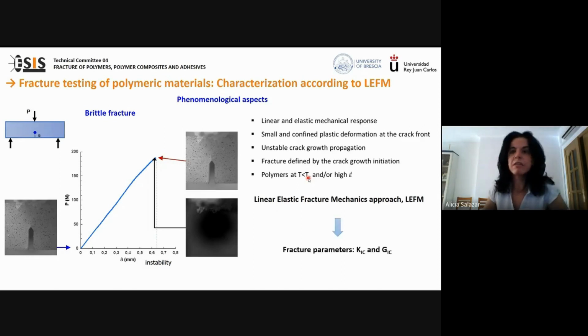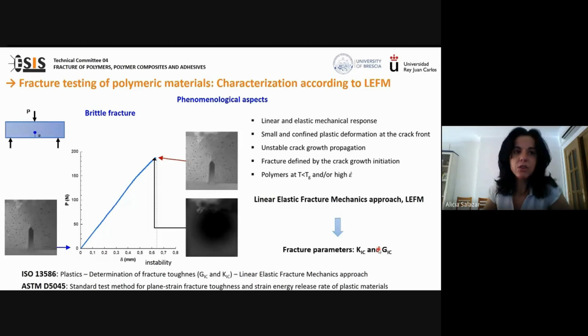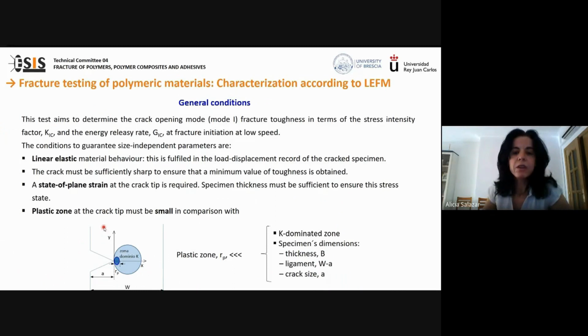The fracture parameters, as already told by Francesco, are the critical stress intensity factor, K1C, and the critical energy release rate, G1C. The subscript 1 corresponds to the crack opening mode. And the standards for the determination of these two parameters are ISO 13586 and ASTM D5045. The aim of this test is to characterize the fracture toughness of plastics in terms of the critical stress intensity factor, K1C, and the critical energy release rate, G1C, at fracture initiation and at low speed. The scheme assumes linear elastic behavior of the cracked sample, fulfilled in the load displacement record.